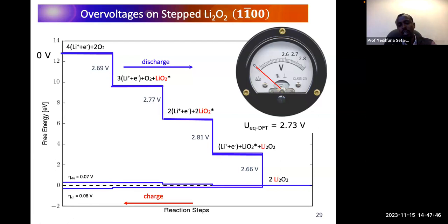So if I want to charge, the third step actually requires a relatively large amount of energy to charge. If you subtract the minimum from the equilibrium and subtract the equilibrium from the maximum, you get the overvoltage. The discharge overvoltage is going to be 0.07, and the charge overvoltage is going to be 0.08, which means in both cases it is insignificant. That means if you apply pure oxygen, there is no overvoltage issue. You see? The overvoltage that we have seen in the experiment is because of the air impurity, because in pure oxygen, we don't find any overvoltage issues.